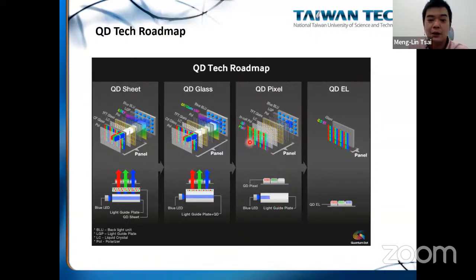Currently the color filters are usually absorption type color filters, so a large part of the energy is lost through the color filters. If we change this color filter to a conversion type color filter, it will save energy depending on your quantum yield. If you have a high quantum yield, your energy loss will be largely reduced. And the final goal is actually to come up with a QD-EL device.